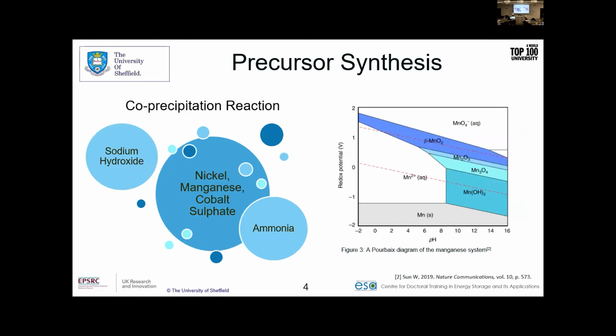So yeah, with regards to this precursor synthesis, we've got the transition metal sulfates here that I've mentioned, and what we need to do with these dissolved transition metal sulfates is collect them all together and form a complex. And in order to form this dissolved complex, we need a complexing agent, which in this case is ammonia. And so we use this so all the cations within the solution are all grouped together. And then when we insert this sodium hydroxide precipitating agent, they all form nice spherical particles. And then that helps improve the tap density when we form the cathodes later on as a proper slurry. And so with more material and higher density, we get more energy density out at the other end, when we actually put them in cells and batteries themselves.